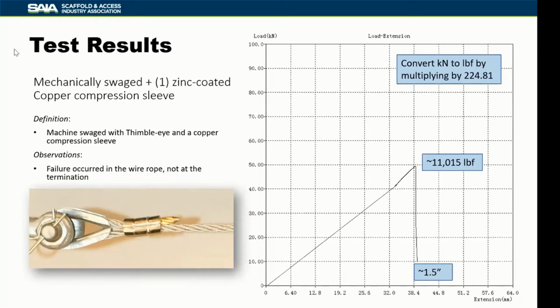although it occurs in the wire rope, often occurs just below the mechanically swaged compression sleeve. So there may be a slight stress riser phenomenon going on there. But again, the failures are typically in the wire rope itself. As you recall, I said that the wire rope that we were using had a catalog breaking strength of about 10,750 pounds. So in this case, we actually got a failure that was higher than the catalog breaking strength of the rope.